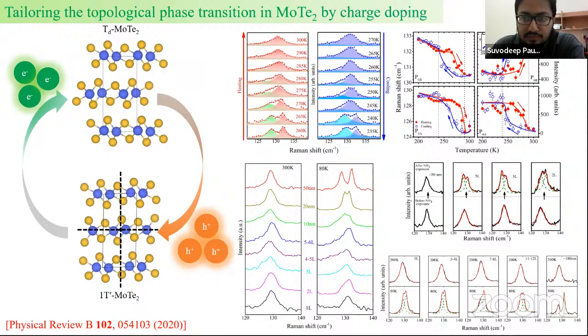Even when you dope rhenium, which phase stabilizes, orthorhombic or monoclinic? Basically, both of them exist, but the phase transition temperature is tuned a bit by rhenium doping. There are also theoretical studies on rhenium doping, which predict that the electron population in the system increases with rhenium doping, particularly in the Td state, which is the low temperature phase. Is the electron-phonon coupling increasing, ma'am? It shows a fairly consistent behavior throughout both the phases.